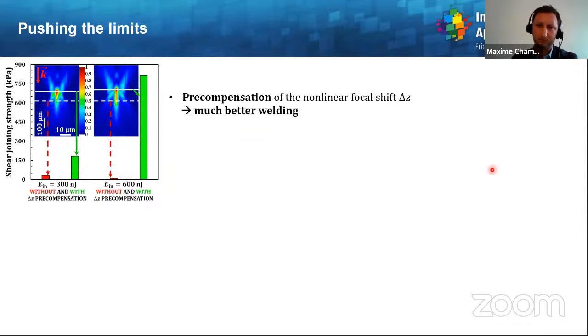So the question now is, can we push the limits even more? Well, to answer this, here I represent the shear joining strength between the silicon and copper for 2 input pulse energies, without in red and with in green precompensation of the nonlinear focal shift. And the striking feature from this figure here is that precompensating the nonlinear focal shift leads to a much better welding.